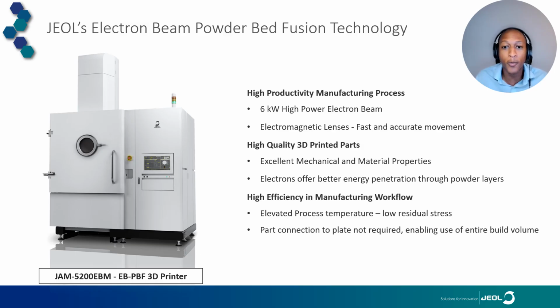Again, with our process, similar to other electron beam powder bed fusion technologies, we maintain an elevated process temperature, which results in low to no residual stresses forming in our parts, and we do not have to have our parts connected to the plate. That enables us to utilize the entire build volume and allows us to place our parts not only connected to the plate, but also off of the plate and around the full Z height of our build envelope.